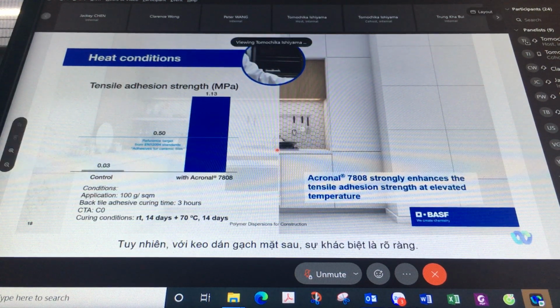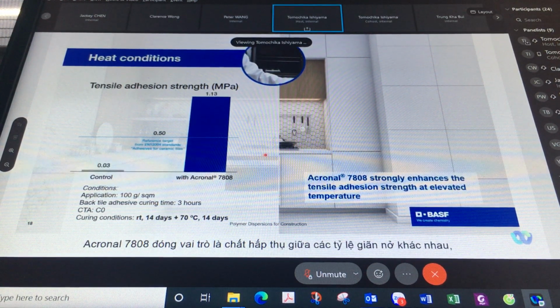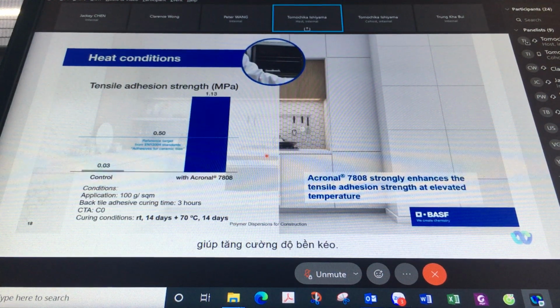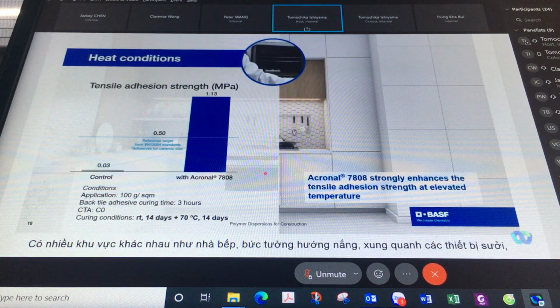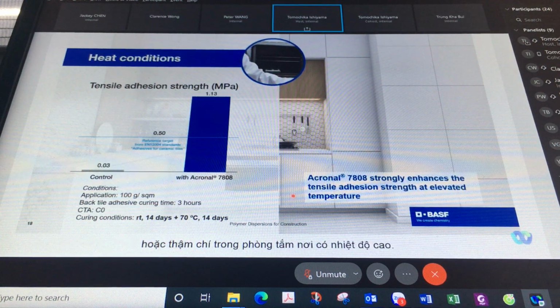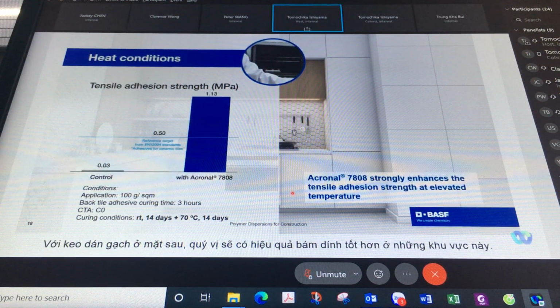With back-tile adhesive, however, the difference is obvious. Acronal 7808 serves as the absorber between the different expansion rates, enhancing the tensile adhesion strength. There are various areas like kitchens, sunlit walls, around heating devices, or even in shower rooms where you have high heat. With back-tile adhesive, you have better adhesion performance in these areas.